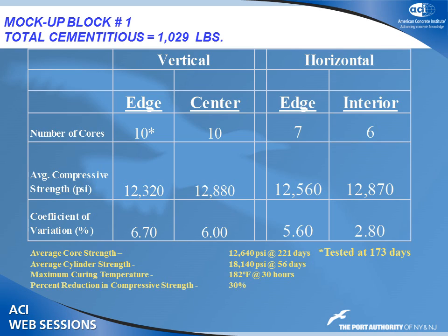Look at the variability in these cores, right? Mike talked about variability. What do you think about this variability? Not too variable. Huh? And this was about 40 cores that we took. Again, we're the Port Authority. We can core till we're blue in the face. And here, this was tested at 173 days. What do you think the maturity of that concrete in place was? It was better than 56 days, trust me. Okay? So, what's the moral of the story here?